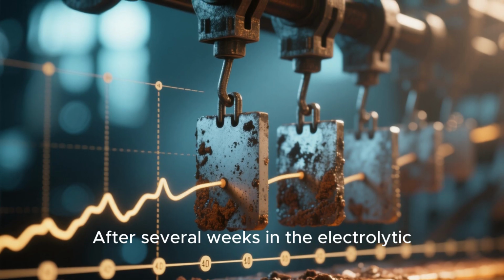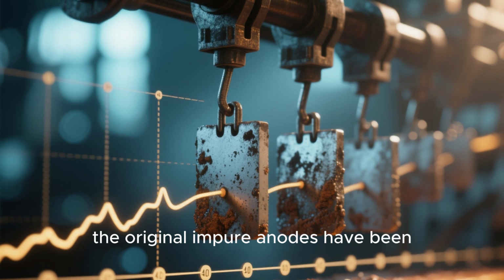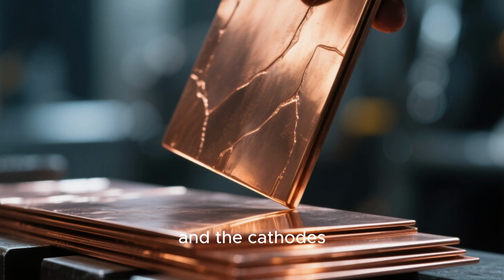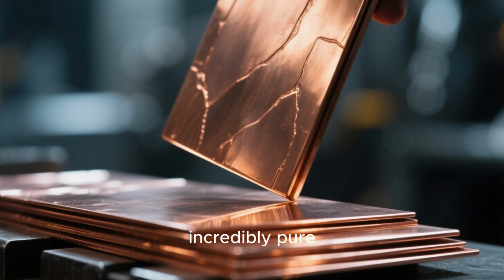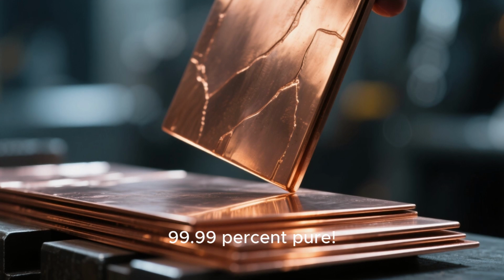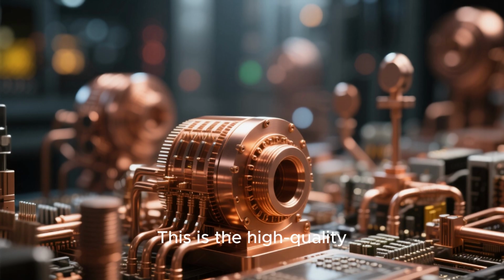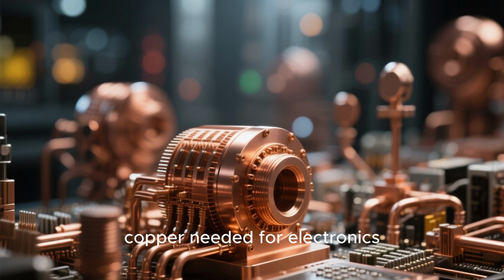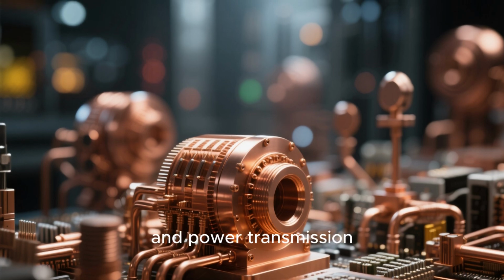After several weeks in the electrolytic bath, the original impure anodes have been mostly eaten away, and the cathodes have become thick slabs of incredibly pure copper. We're talking 99.99% pure. This is the high-quality copper needed for electronics, telecommunications, and power transmission.